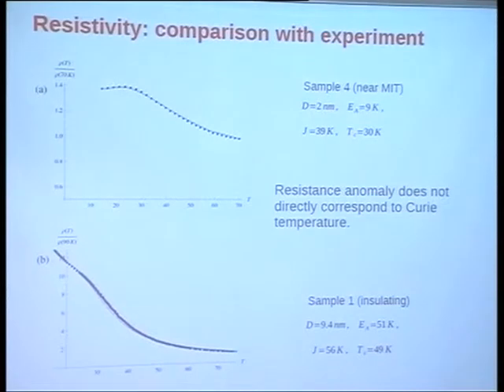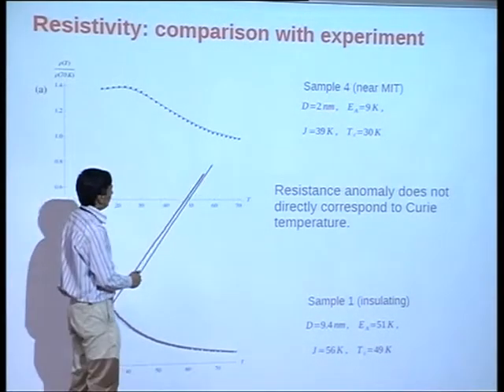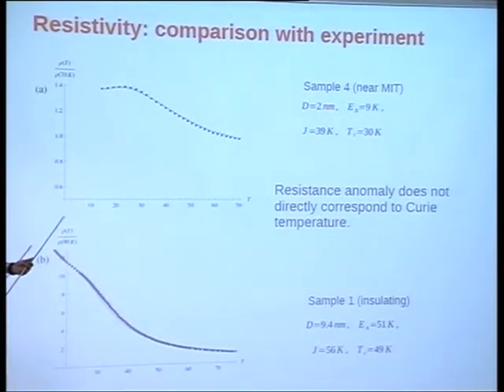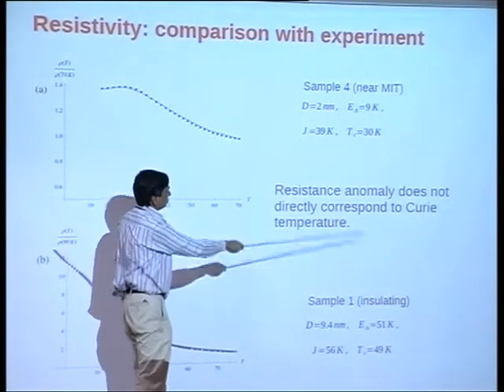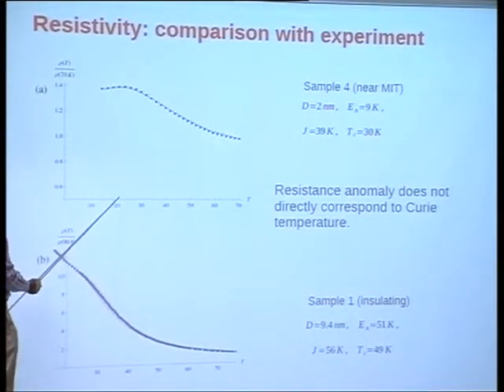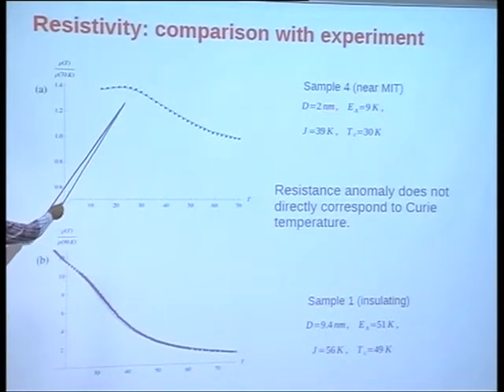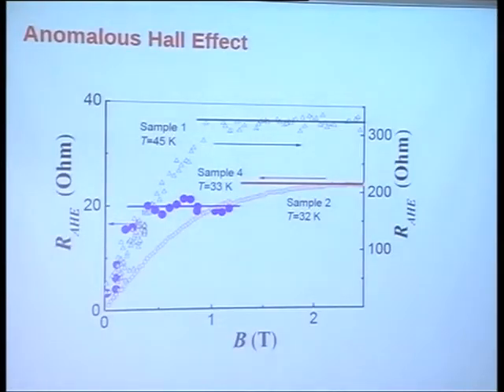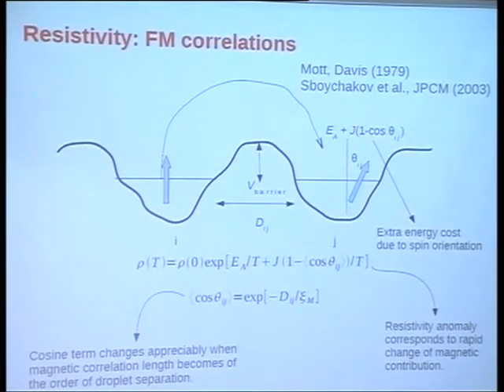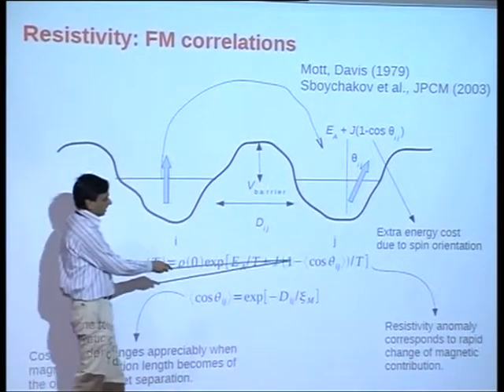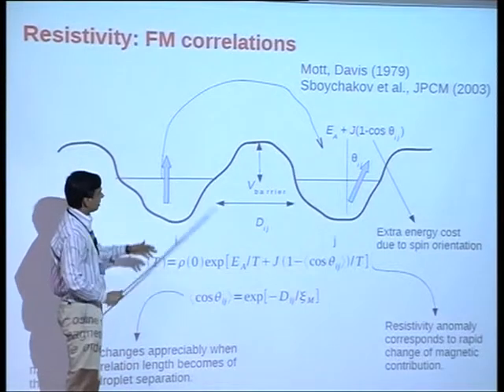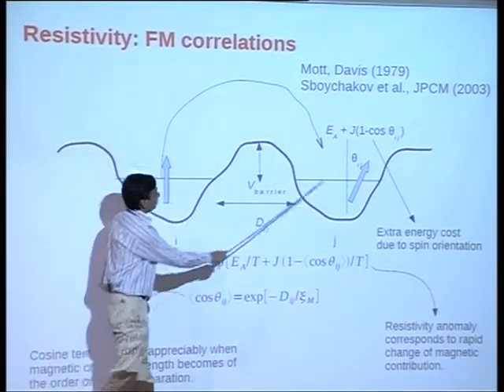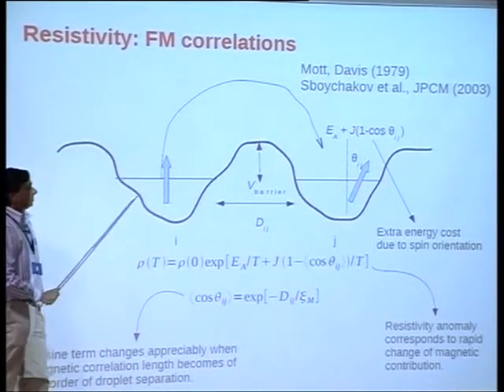So this is a fit to the isotropic Heisenberg model, and as you can see, the data can be relatively well explained by fits of very crude, simple-minded modeling of this kind. We can extract transition temperatures, Curie temperatures, and generally we notice that the Curie temperatures tend to be higher than the point at which the resistivity anomaly appears. And the reason is not that hard to see. The resistivity shows the maximum change whenever the correlation length becomes long enough that it becomes comparable to the interdroplet distance. So it doesn't have to go to infinity.